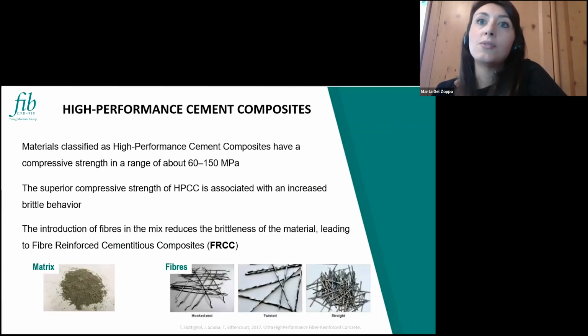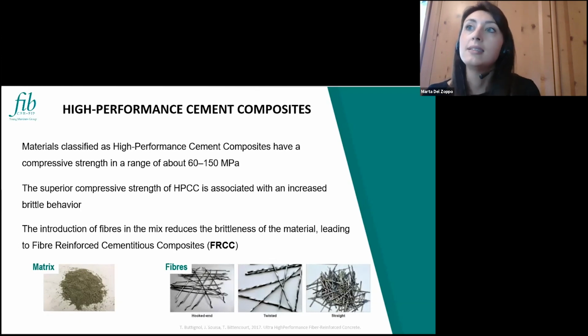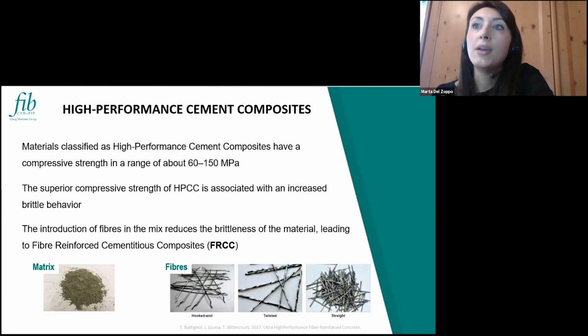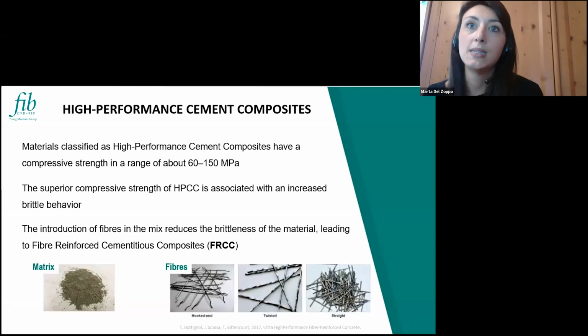Today, we are looking at a class of relatively new materials that are classified as high-performance cement composites. These materials are characterized by high compressive strength, up to 150 megapascal in compression. And of course, this increase in compressive strength has a drawback, that is the brittleness of this material. So to contrast this brittle behavior, we can add fibers, so short or long discontinuous fibers inside this material can improve the tensile behavior of the material itself. And this kind of material is called fibre reinforced cement or cementitious composites.